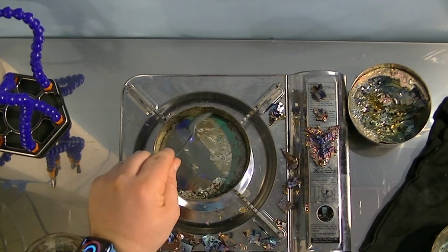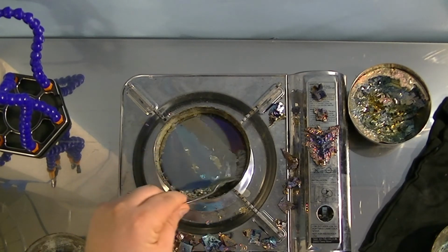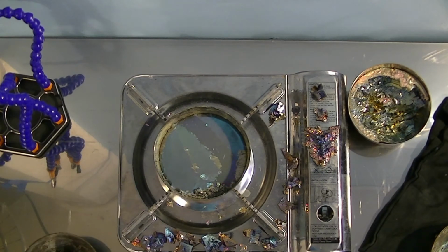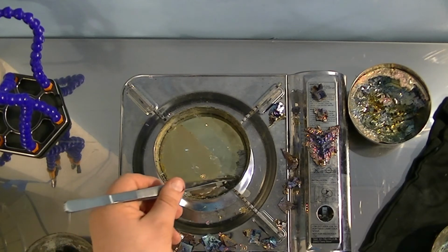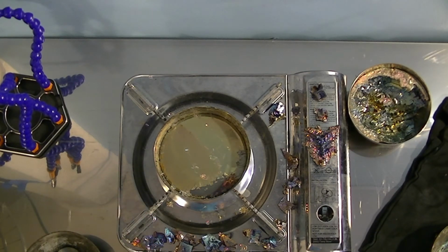One of the things that works in favor of this is that the bismuth, as far as I can tell, stays pure by probably rejecting impurities to the surface as it freezes. So despite probably hundreds of cycles of melting and remelting, I still keep getting good crystals that indicate high purity. And when I've seen people who've tried to use lower purity bismuth to make crystals, it doesn't really work well for them. So I don't have to worry about that, at least. Not only does it seem to not pick up impurities, it also doesn't seem to gather impurities from the tools that I use. That is, the iron or nickel or chromium in the stainless steel implements I'm using, or the stainless steel bowl here, don't seem to become part of the melt at all. At least not in any appreciable concentration. That also works for me.